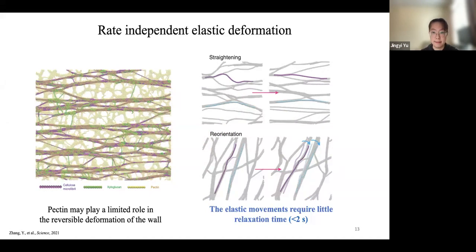And we can see that, combined with our molecular insights from a recent modeling observation, where we saw that the elastic deformation mainly comes from the straightening as well as reorientation of elastic cellulose fibers, our results suggest that this elastic deformation requires very little relaxation time, at least less than 2 seconds, so overall this deformation appeared to be rate independent in our experimental condition.